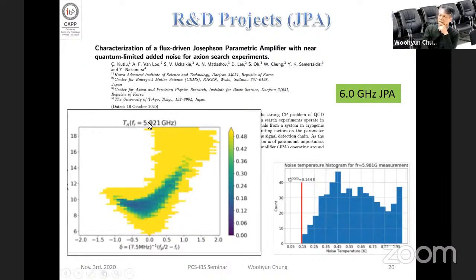This JPA result was testing 6 gigahertz and 2.3 gigahertz. This one is around 6 gigahertz. We are trying to optimize and find the point which gives the lowest noise temperature. We made this kind of map, and this is a histogram collecting all the noise temperatures. In all those cells, we measured the noise temperature, and this is the result. The lowest one for this 6 gigahertz JPA was around 150, which is close to the standard quantum limit.